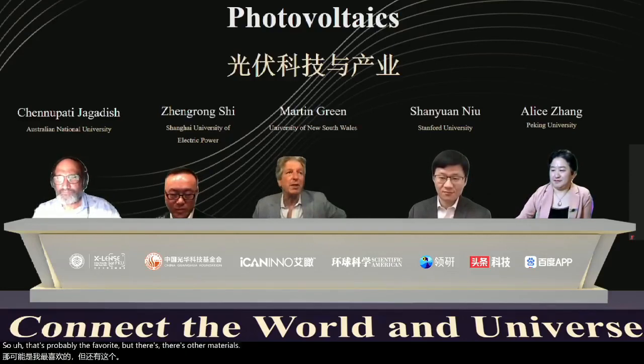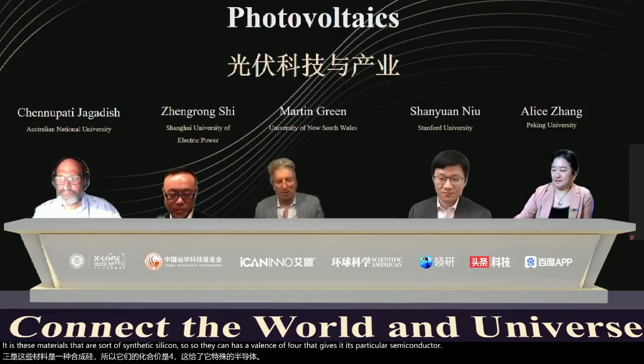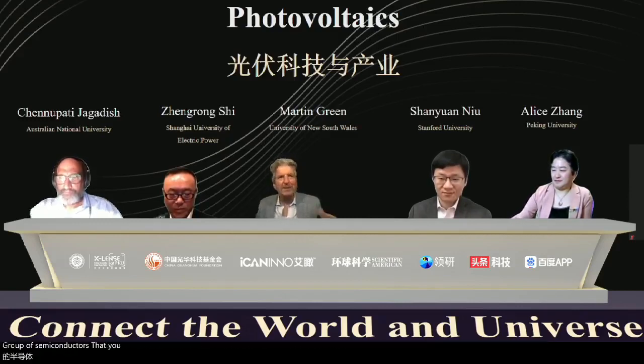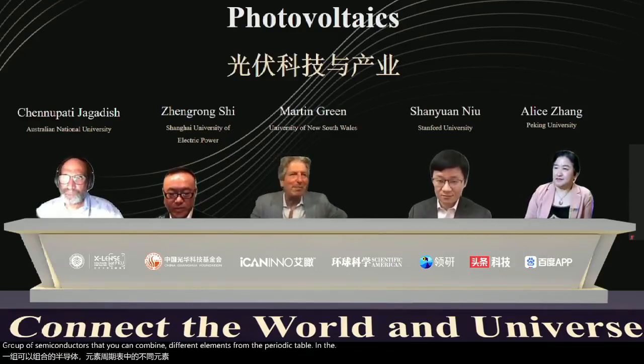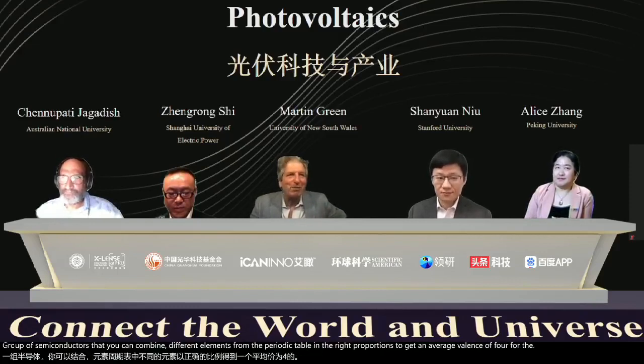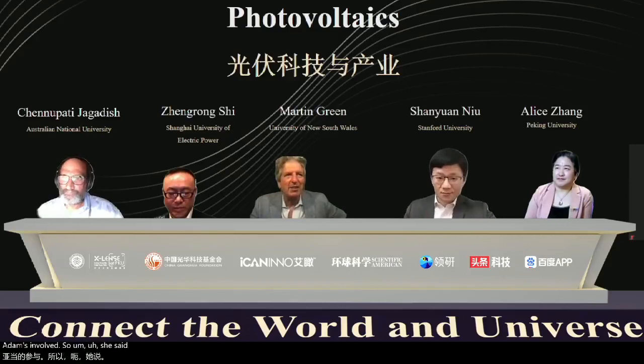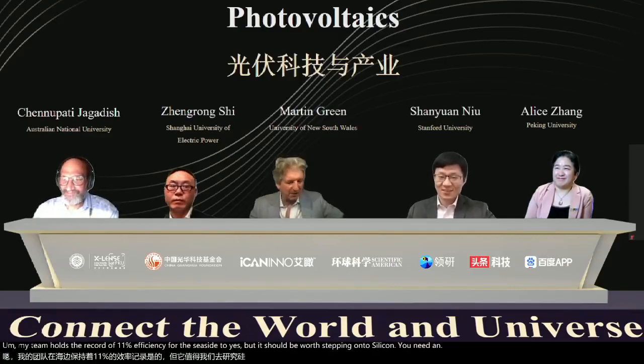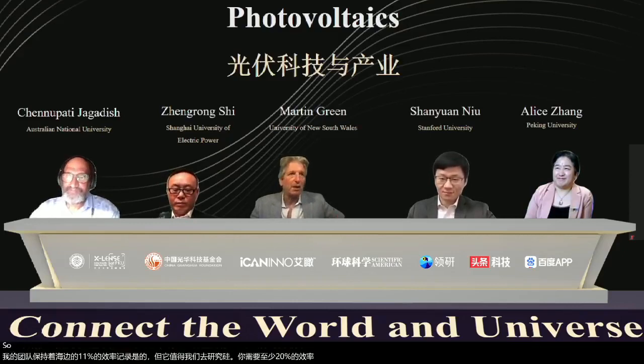Then there are other materials like copper, zinc, tin, sulfide. These are materials that are sort of synthetic silicon. Silicon has a valence of 4 that gives it its particular semiconductor properties, but there's a whole group of semiconductors where you can combine different elements from the periodic table in the right proportions to get an average valence of 4 for the atoms involved. So CZTS, copper, zinc, tin, sulfide, is one that has 3 ticks. It involves abundant, non-toxic, stable materials, but getting the efficiency to a reasonable level is a problem. My team holds the record of 11% efficiency for the CZTS, but to be worth stacking onto silicon, you need an efficiency of at least 20%. So we've still got a long way to go with the efficiency.